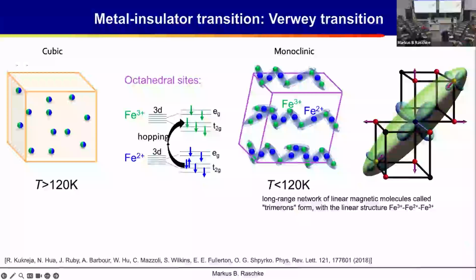Yeah, so above 120 Kelvin, it is cubic, and then below 120 Kelvin, it is monoclinic. So the crystal structure tilts, the unit cell angle changes between these three crystallographic axes. So exactly at the transition, you have quantum fluctuations. This is also a regime which is very poorly understood, where the system fluctuates between these two phases. And how sharp this transition is: ideally for a first order phase transition, this is exactly a sharp transition. So even an infinitely small increase in temperature would put it on one side, and an infinitely small change to the other side would switch it in the other direction. That is the ideal case for such a quantum phase transition.